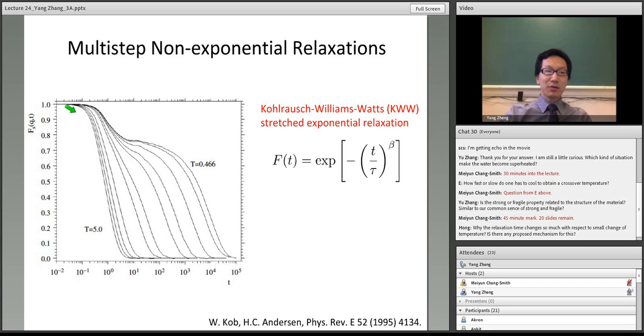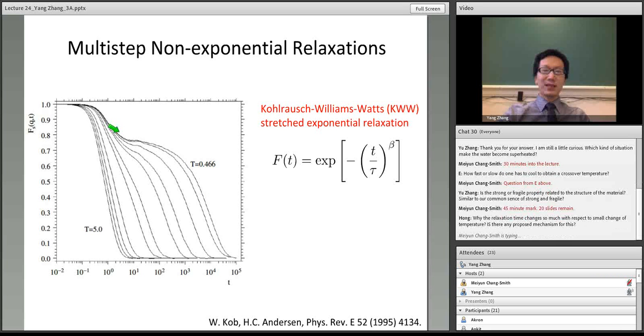So at a very short time, you can see that the intermediate scattering function, or in other words, the density correlation function, doesn't decay very much. This is basically the ballistic region. And when we go to longer times at low temperatures, there are two-step decays. The slowest one is always called alpha relaxation, and the fast one is called beta relaxation.